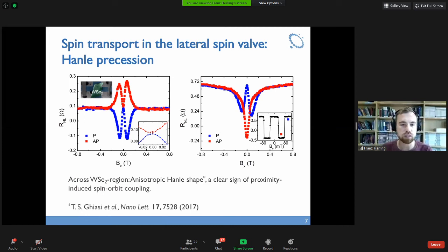The reason for this is that in the diffusion equation, the overlap between the parallel and anti-parallel curves actually gives you the anisotropy. So it's always expected that those two curves overlap. And as you see in the inset on the left side, in our case, they didn't overlap. So we were not able to extract the out-of-plane and in-plane lifetime, and so the anisotropy ratio for the graphene, due to those two curves not overlapping.